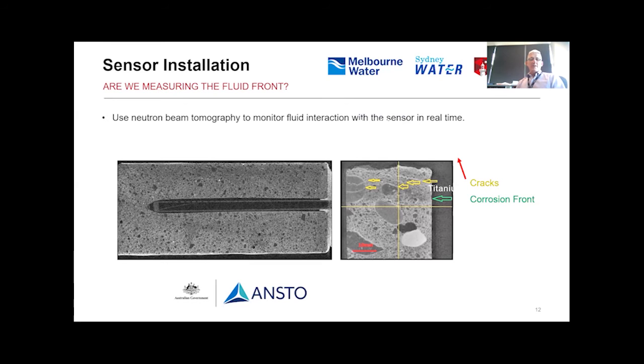And so on that left-hand image there, the cross cutaway section, you can see a cross-section through one of our grating features, our relative humidity probes. You can just barely see the fibre there at the very bottom of that probe. You can see the porous section in the 3D printed section. But what we noticed is as the fluid front moves through that sample, it will wick around this particular sensor, and the sensor will detect nothing. So again, this told us a lot about the strategies we had to develop with respect to implementation and installation of these particular sensors.